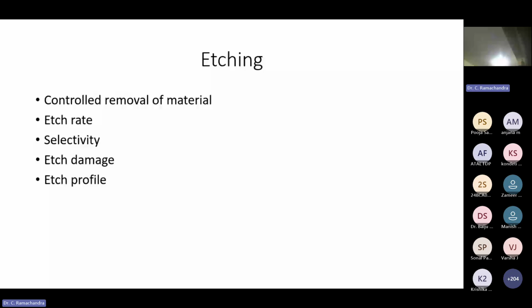And etch rate is important because productivity is important. I cannot take a few hours or a few days to etch it. Selectivity is very important. That means I want to etch silicon, but I should not etch the adjacent silicon dioxide. I want to etch silicon dioxide, I should not damage the adjacent silicon nitride. Like that, we have a lot of constraints. Selectivity means I want to etch one material without damaging or etching the other material. So how best can I do it?